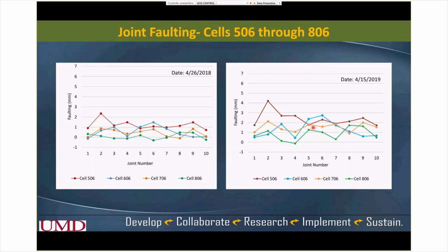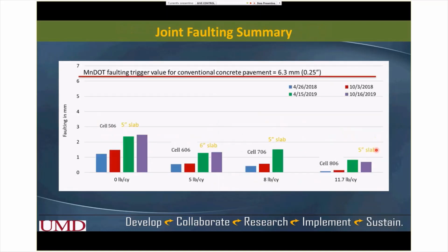Here we see a clear picture of how the fiber is contributing. Let's look at the data we have for April 2019. You can see the plain concrete, the red one, has a higher amount of faulting, and the green one, 806, which had the highest amount of fiber, had less faulting. Then we put all those average faulting results together in this plot, and as the fiber is increased, faulting is decreasing.